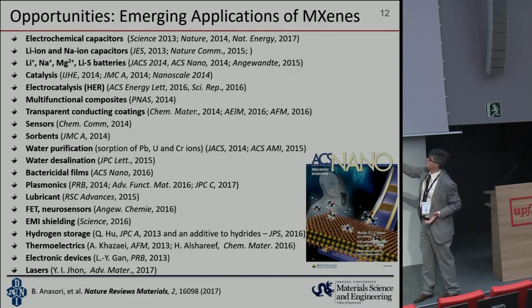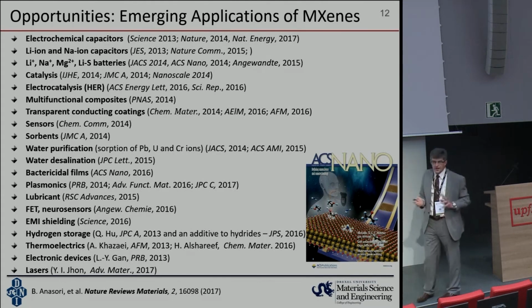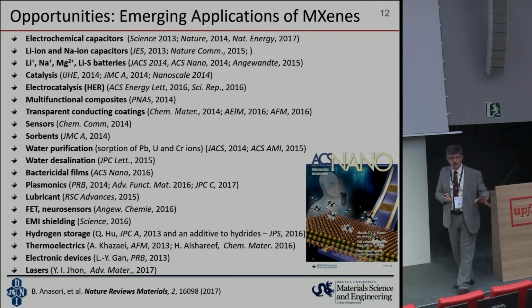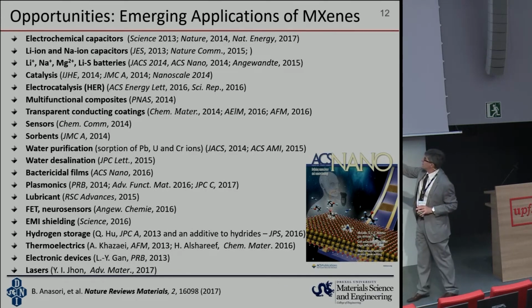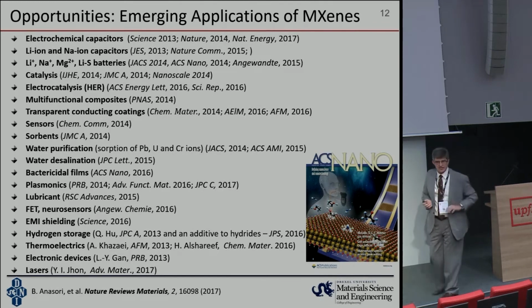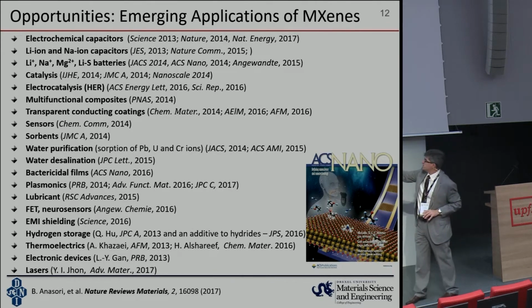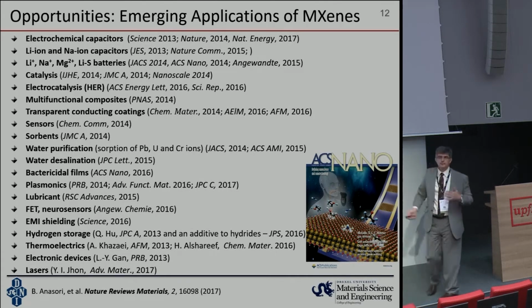Lithium-ion, sodium-ion capacitors, lithium, sodium, magnesium, also aluminum, lithium-sulfur batteries, electrocatalysts, composite materials, transparent conducting coating, sensors, sorbents, water purification. They can remove lead, uranium, chromium ions, even from seawater in presence of smaller ions because of a strong interaction with multivalent ions here. Water desalination, both membrane and capacitive. Plasmonics based on plasmon resonance of metallic materials here. Sensors, electromagnetic shielding, and many others.